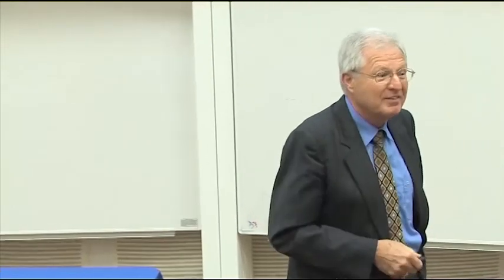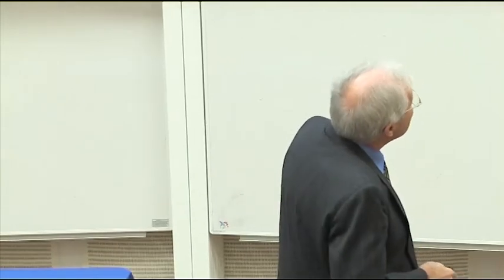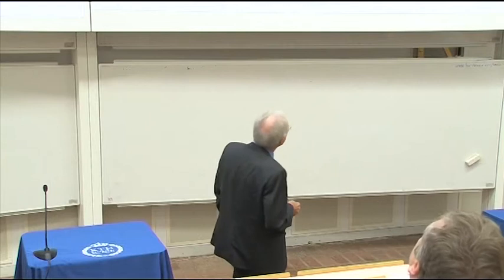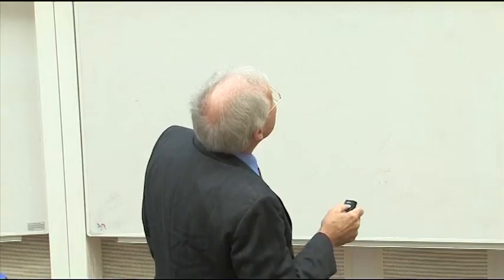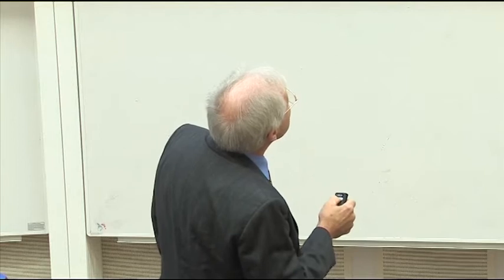Now, the calculation we did is for 4% chromium doping. You remember, maybe you remember the red and the blue points I had in my first picture. And now this lattice constant changed slightly, not much. There's a slight distortion, namely that this thing goes a little bit apart from each other. And that thing now has this, as these two get a little bit apart, that this thing has a drastic effect. It goes from 0.49 to 0.41.